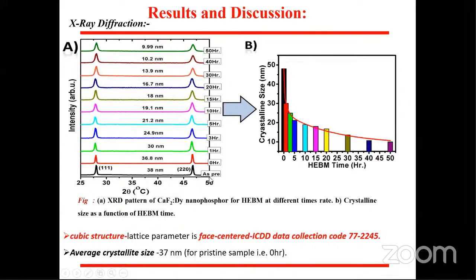In X-ray diffraction, the as-prepared sample indicates a very small FWHM. In the 50-hour ball milled sample, we got a crystallite size of around 10 nanometer, and FWHM also increases. The second figure indicates how the crystallite size is reduced. We also confirmed using JCPDS card number 77-2245, and the structure shows a cubic, face centered lattice. The average crystallite size for the pristine sample is around 38 nanometer.